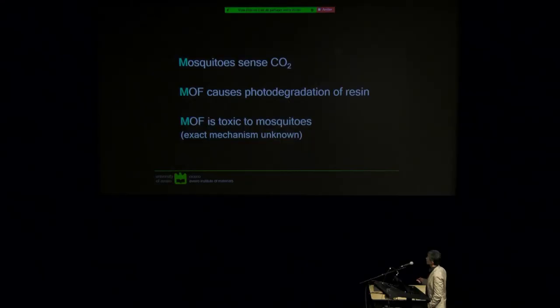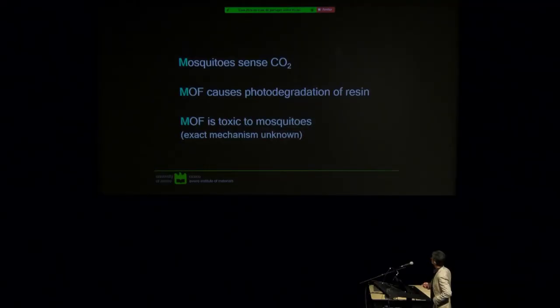Now, if we wash the nets 5 times, we still have 68% mortality. So a lot remains. And how does it work? We don't know exactly how it works. What we know is that mosquitoes sense CO2 and temperature, and the MOF causes some photodegradation of resin. So this resin, which imparts mechanical properties, is decomposed, some CO2 is probably produced, and this attracts mosquitoes.